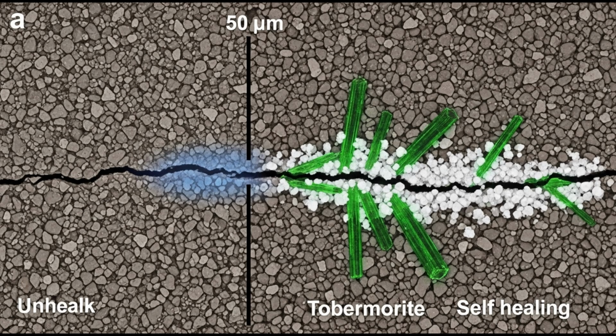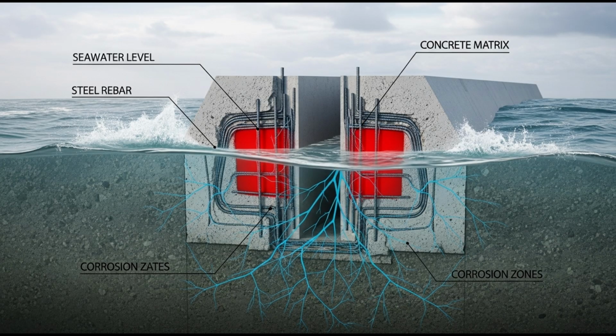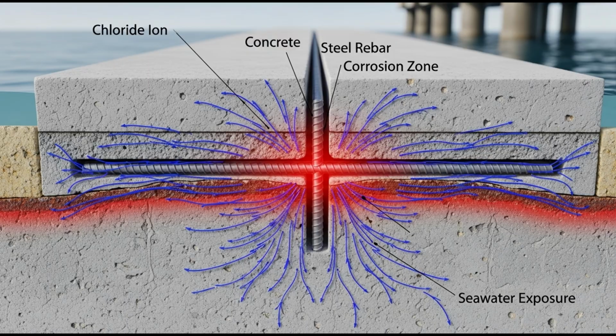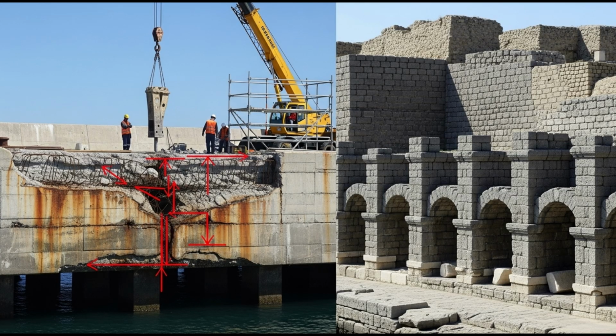One is static. One is dynamic. Both work initially. Over centuries, dynamic wins. Marine environments. This difference is most pronounced in seawater. Saltwater is catastrophic for modern concrete. Chloride ions from salt penetrate, reach the rebar, initiate corrosion. Rust expands. Concrete cracks. Accelerating failure.